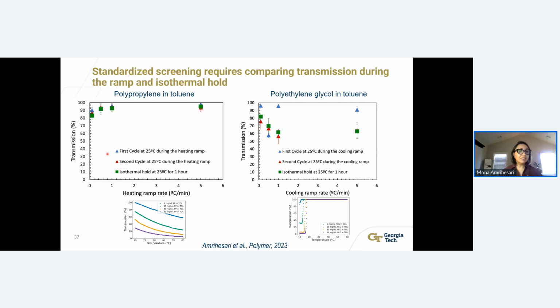So as you can see, this data is matching perfectly, meaning that as we observed, the kinetic is fast enough and the data is reproducible, so we can rely on even extracting all the data during the ramp, because this gives us information, and it has a lot of information from 10 degrees C to 60 degrees C that we can use. Something that has not been done before, because all the data was just collected at one temperature with some instruments, and we didn't have this knowledge on a variety or range of the temperature.